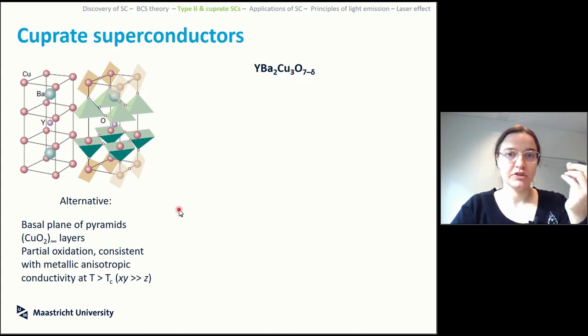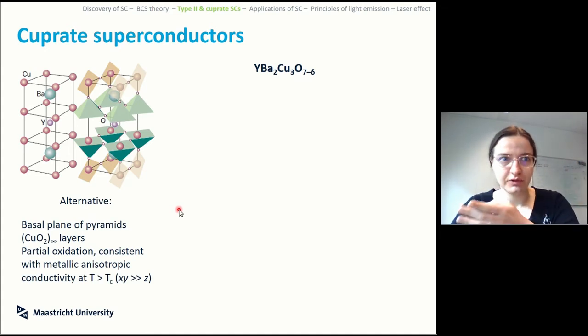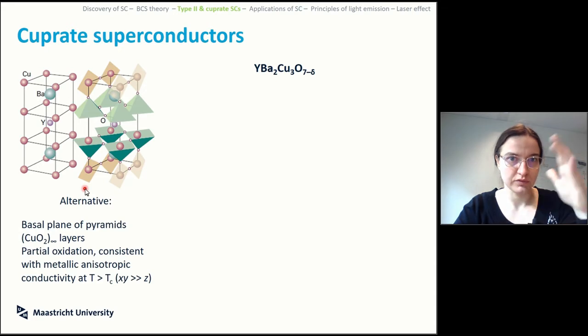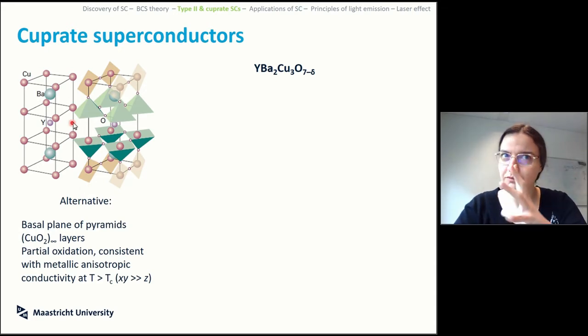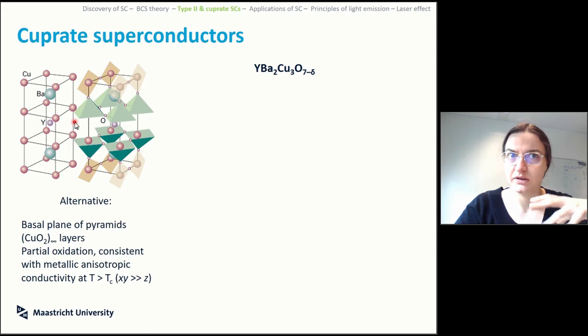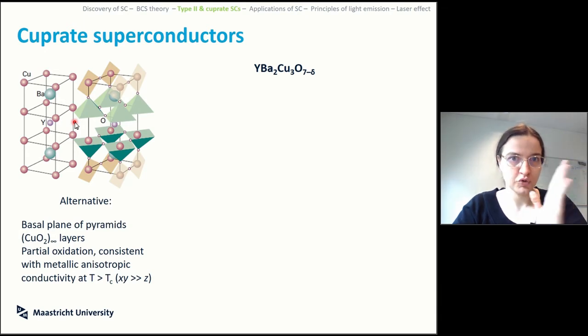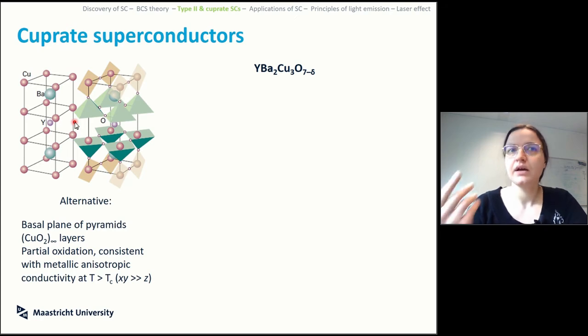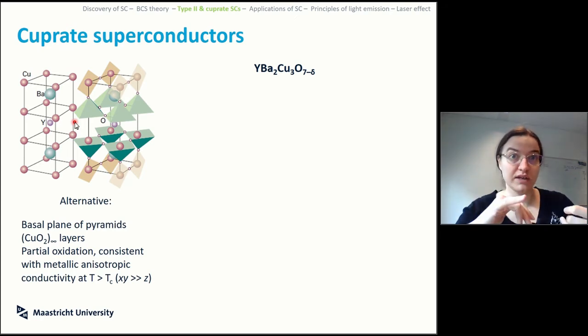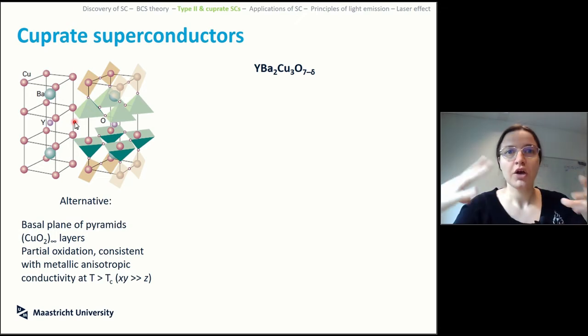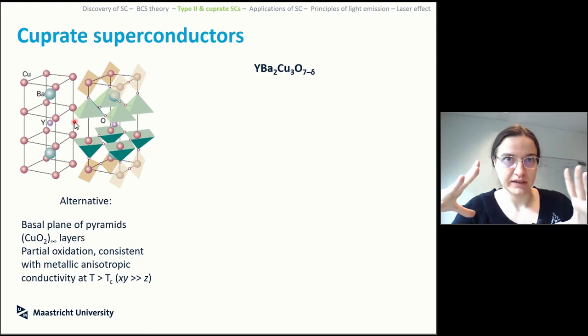Now this means that the oxidation state in yttrium barium copper oxide, if you assume that you still have yttrium, barium and oxygen in the usual oxidation state, so 3, 2, minus 2, even though there are some wondering about whether this oxygen is actually a bit weird, so you have oxide ions as oxygen minus instead of oxygen 2 minus. That's an additional argument. But if you assume the 3, 2, minus 2 arrangement of yttrium, barium and oxygen, then this leaves you with a mixed valency on the copper, which is something that we already seen in batteries and stuff like that, because if you can change the oxidation state, it means that statistically speaking, throughout your structure, you should have an average of 2.33, something like that.